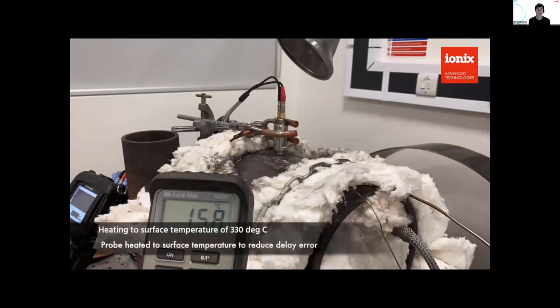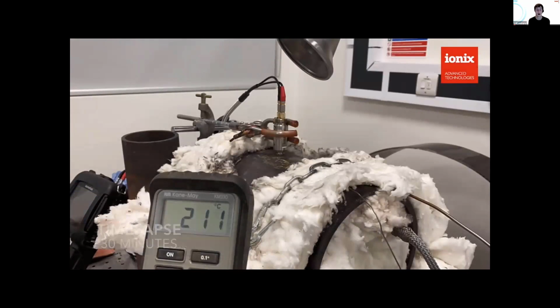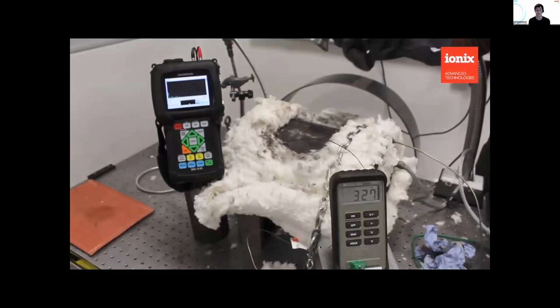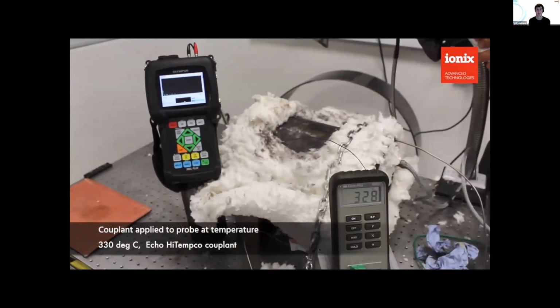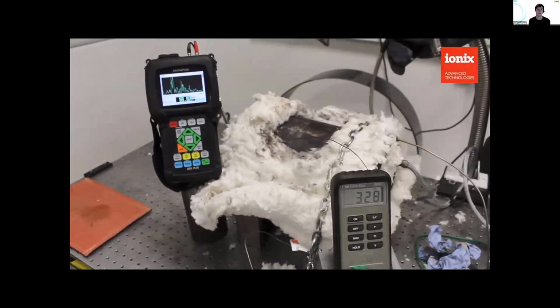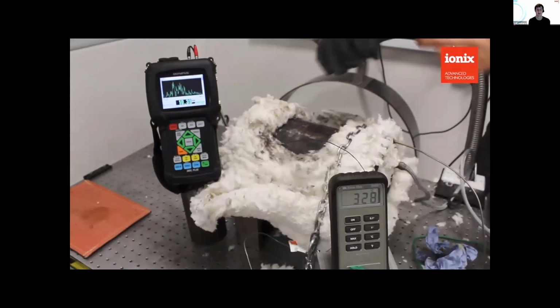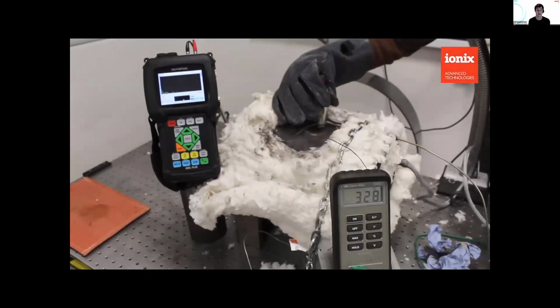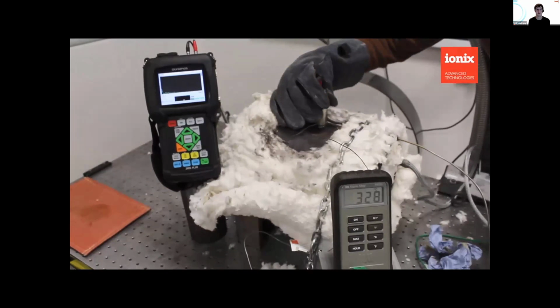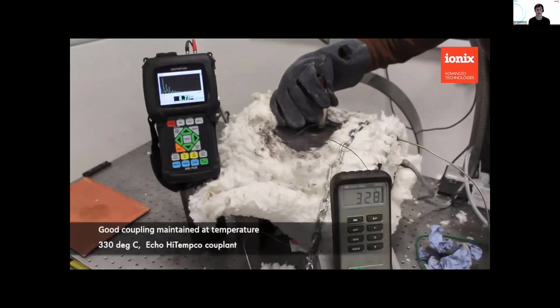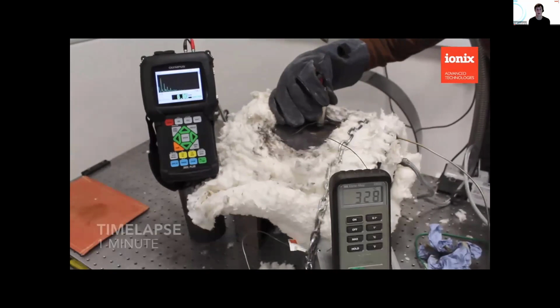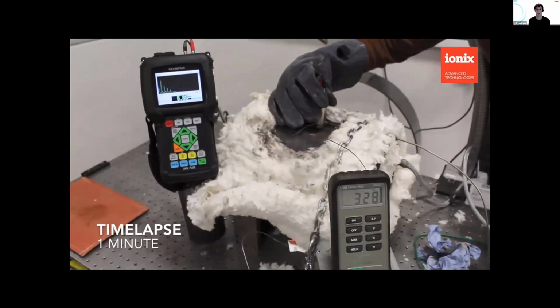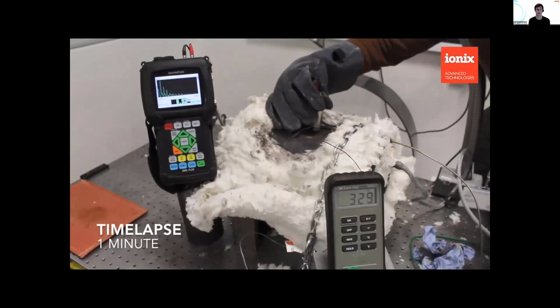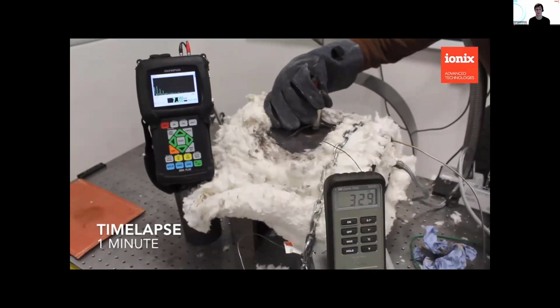But here you can see, sped up, it's being held on a pipe which is being slowly heated up over 30 minutes to 330 degrees C. The probe is fine, with no change in its operation. As proof of that, it's very quick and very easy to take spot measurements using the probe. At this point, the probe has heated up. The probe is hot because the user's wearing gloves, and the pipe is also hot. It was left on for a long period of time here and able to collect very stable and repeated measurements.